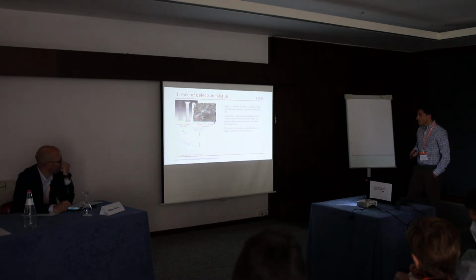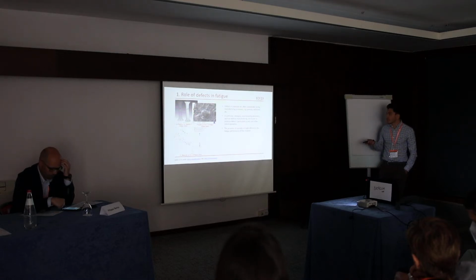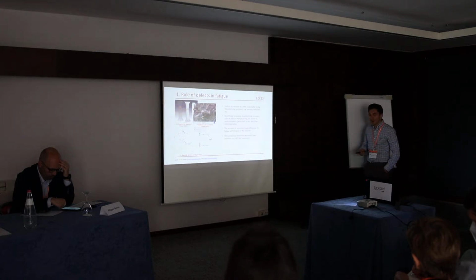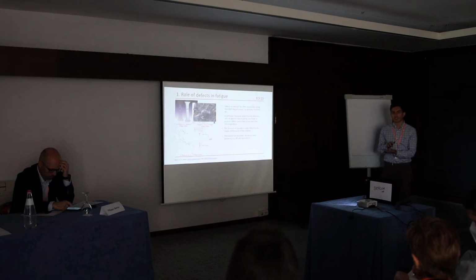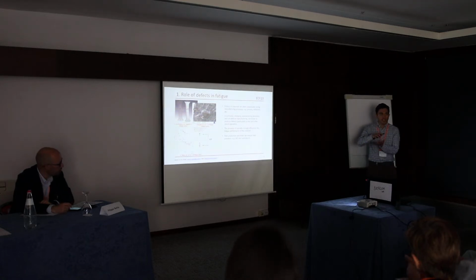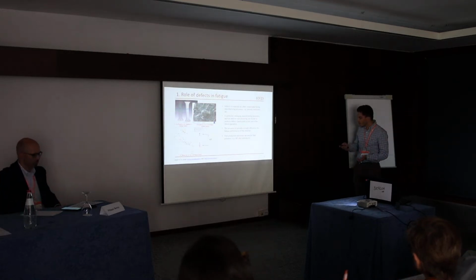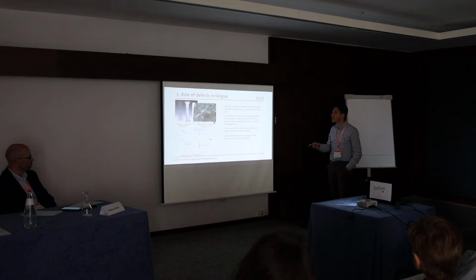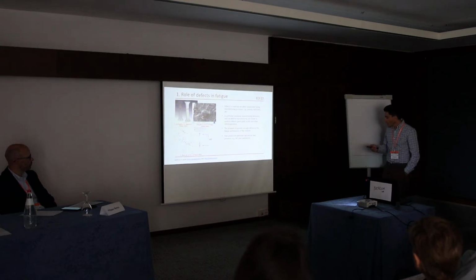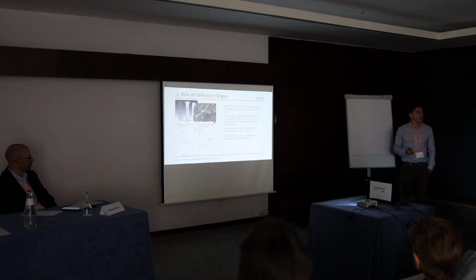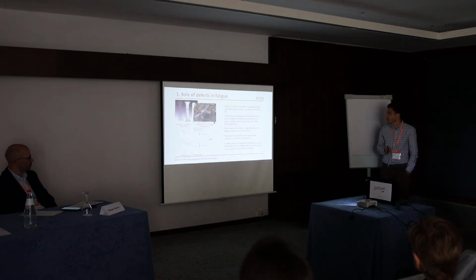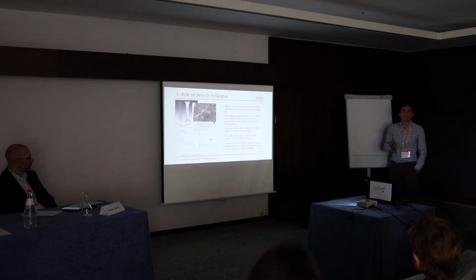We can also see from literature that the influence of porosities in particular is very strong as concerns the fatigue properties of these materials, and we can also see that if we apply some thermomechanical treatments to these manufactured materials, we can actually improve the performance a lot. For example, if we apply this HIP process, so basically we close all the pores, we can improve the fatigue properties 2, 3, even 4 times. Obviously, for practical applications, if we deal with real components, it's not always doable. We cannot post-process all the components. So we need to develop a model that can account for the defect population of materials, and then we need to live with that.